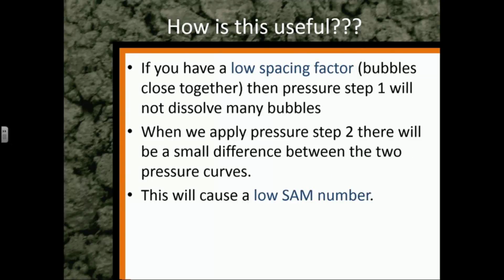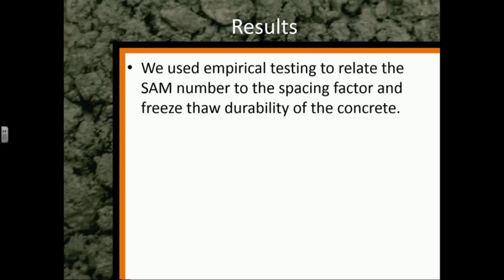If you have a low spacing factor, bubbles close together, then pressure step number 1 will not dissolve very many bubbles. So when you apply pressure step number 2, there's going to be a small difference because the bubbles are still there. When you go and you punch it the second time, a lot of those bubbles are still sticking around. So it's going to behave similarly, not exactly the same, but similarly to how it did the first time. And this is going to cause you to have a low SAM number. So we've used empirical testing basically to relate all of this to the SAM number, to the spacing factor, to the freeze-thaw durability of the concrete. And that is how we use the SAM number to predict freeze-thaw durability.